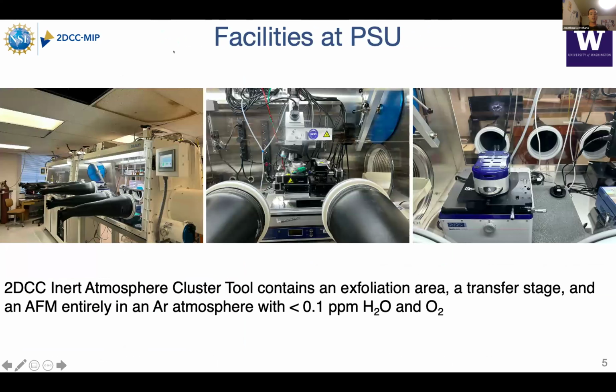And so the reason that I really wanted to come to Penn State was the 2DCC inert atmosphere cluster tool, where conveniently you could do all the steps I just mentioned inside of a glove box with an argon atmosphere of less than 0.1 part per million water and oxygen. This is very important because these new materials that I'm interested in often get very air sensitive as you thin them down. If you're just doing it in air, you'll do all this work and you'll be left with nothing, whereas if you do it in a glove box, hopefully your flakes will be more or less safe.